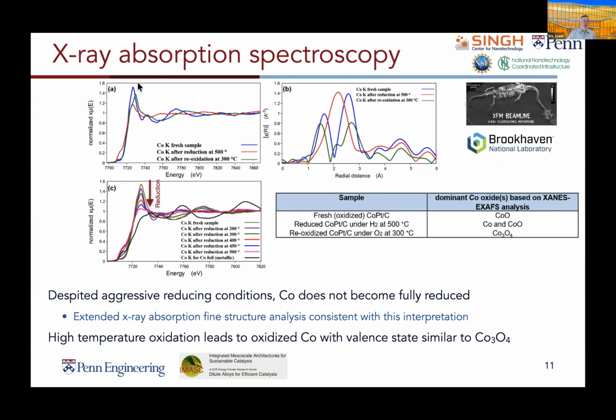We see changes in the near edge structure, which are consistent with changes in the electronic structure of the cobalt. We can see that as we increase the temperature in hydrogen, we're able to get more and more overall reduction of the catalyst, bringing it towards a more metallic state. But when we compare that with pure metallic cobalt, it hasn't reached the whole way. So that indicates that even in these very aggressive environments of high temperatures with pure hydrogen, we're unable to reduce these catalysts completely to the metallic state.